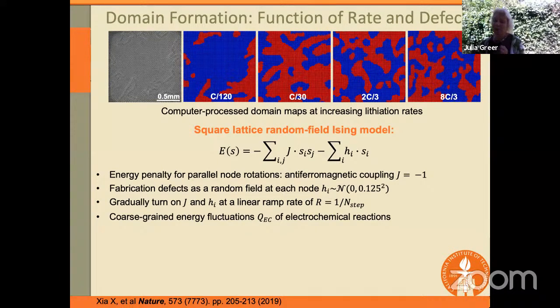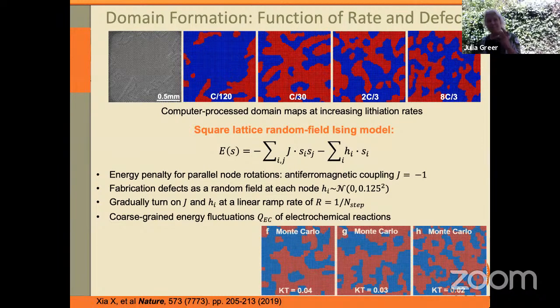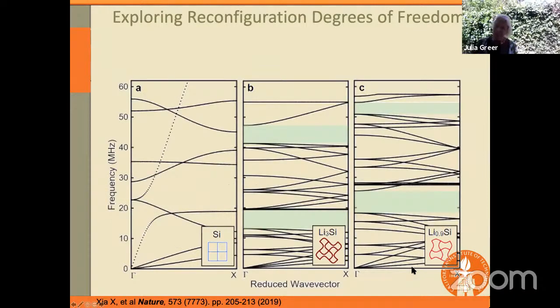So once you incorporate a coupling coefficient and start to recognize that there's a correlation between the rate parameter, which in our case is the lithiation rate, and in the case of the Monte Carlo simulations is this kT parameter, so it's the thermal contribution, we can see very similar behavior. These images at the top are actual renditions of our SEM images, and the images on the bottom are computations. And so what we were able to show is that there's a band diagram that you can create as a function of lithiation. So when you start off with pure silicon, there are no band gaps. Of course, you have every state occupied.